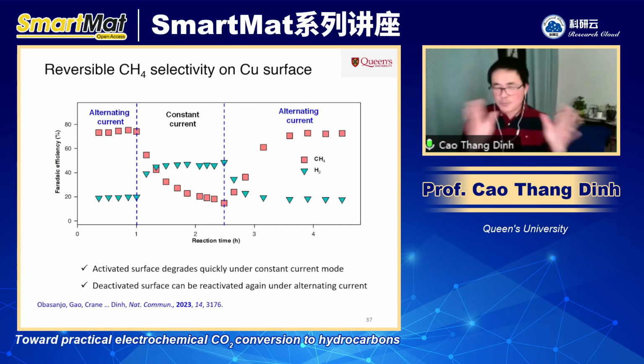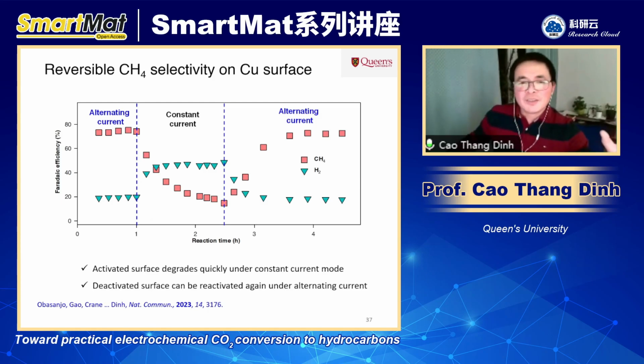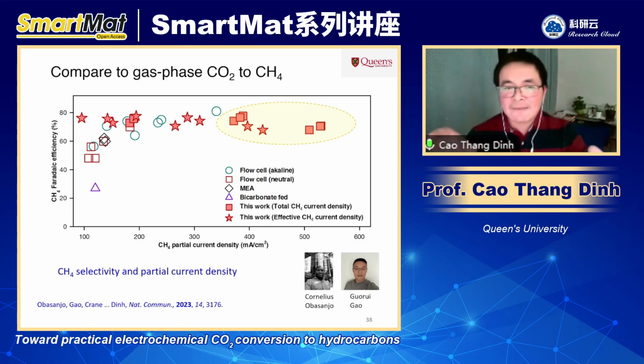Okay, so I have shown you a pretty good selectivity and the reversible property. Now, the question is, how does this compare to the gas phase conversion? Right, so in this graph, we compare the selectivity versus the methane partial current density of the aqueous system. Now, even with the aqueous system, we can have high selectivity and high current density as well compared to the gas phase CO2.